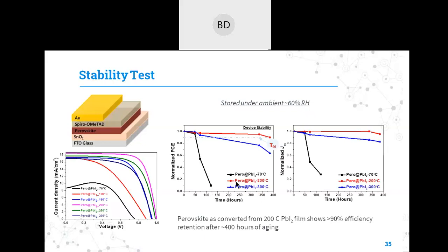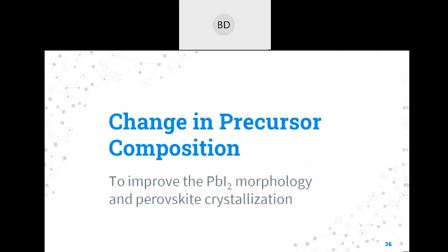But the perovskite which is prepared at 200 degrees centigrade has been retaining more than 90% of efficiency even after 400 hours of exposure. So it shows that there is a significant improvement in the stability of the perovskite films prepared by the two-step method if we use elevated annealing temperatures of the lead iodide film. So this was the one approach that we have used to improve the two-step methodology.